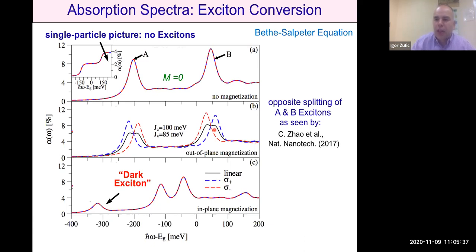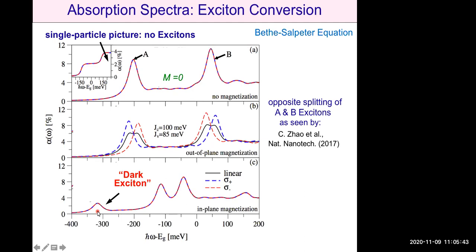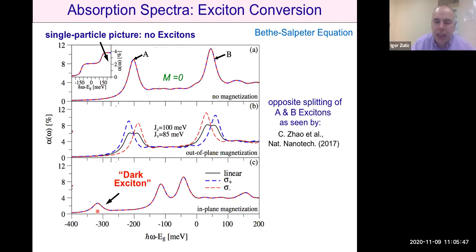But what is interesting, if we go to this seemingly boring case of in-plane magnetization, we have now a new feature. And this new feature can be viewed as a dark exciton. So we are able to brighten the dark exciton and have this new spectral property. So in other words, just a simple change of direction of magnetization can strongly change optical spectra and give us